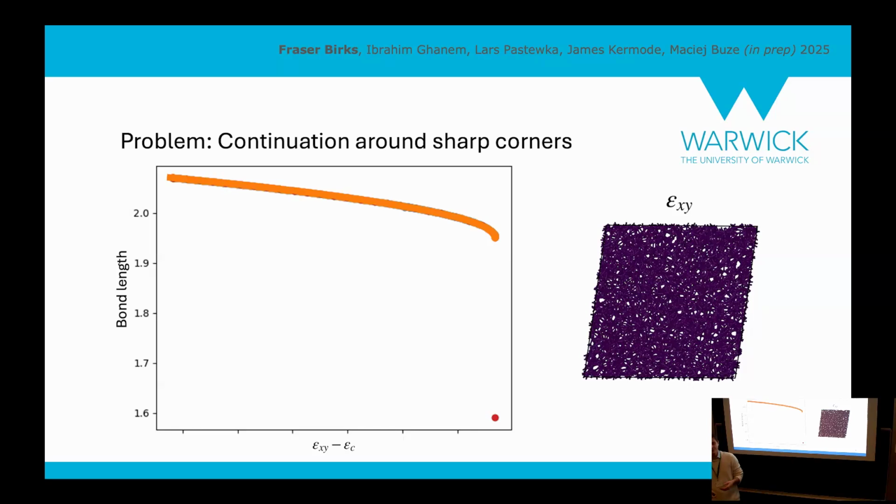So this was fine for single bonds because, as I say, about 70% of them still worked. But when you're trying to walk through an entire avalanche, which is say like 8 bonds long, right? If 20% or 30% fail, you just can't get through the avalanche. It's just impossible because almost all the time you fail, right? You could do it very occasionally, but it was quite rare.